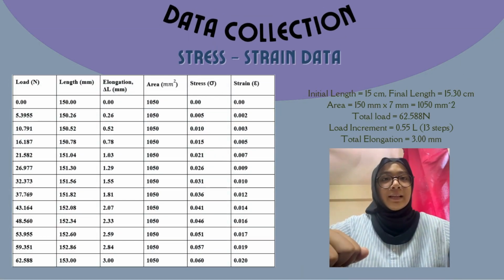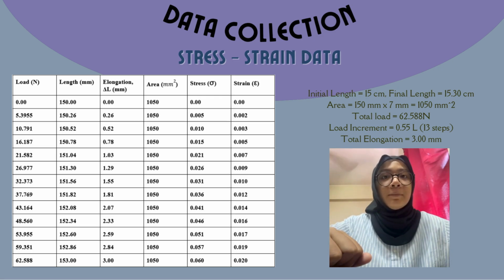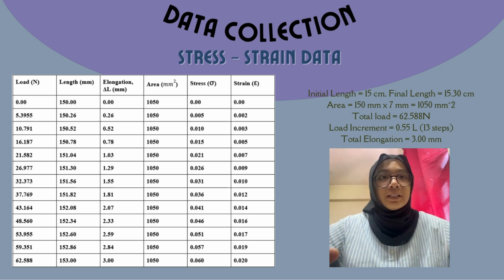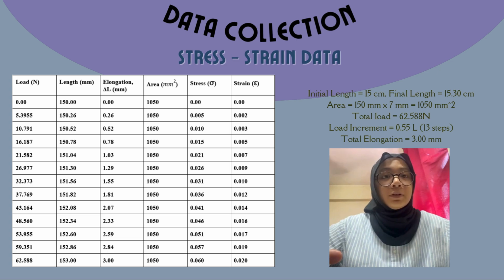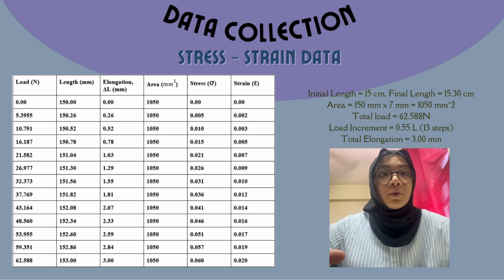Moving on to the quantitative analysis of our experiment, this slide presents the stress-strain data table recorded during the loading process. The specimen had an initial length of 150 mm and a calculated cross-sectional area of 1050 mm squared. We conducted the test using a control load increment of 550 ml, which resulted in a total of 13 recording steps. As we observed the data, the load was increased from a baseline of 0 Newton to a final total load of 62.588 Newton. Throughout these increments, the specimen exhibited a steady increase in elongation, reaching a total of 3 mm. This resulted in a final specimen length of 153 mm or 15.3 cm.